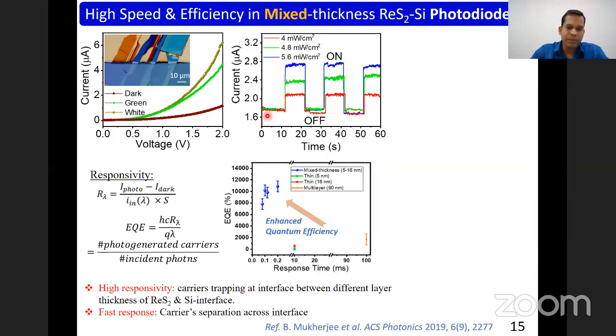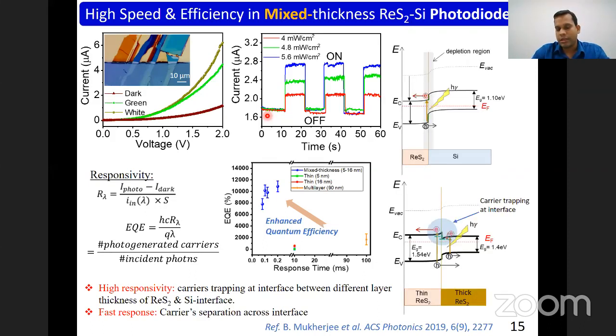And from there, we extract parameters like responsivity and external quantum efficiency, which shows that the mixed thickness ReS2-based device shows a high external quantum efficiency with a fast response of around 10 milliseconds. And that we explain from this band diagram as shown here. So this type of device not only has this depletion region across the silicon interface, but also has those edge states at the interface between thin and thick. Those edge states also play a major role in the device response, because they trap carriers so that it increases the carrier lifetime for holes, and that circulate in the external circuit to increase the responsivity value of the device.